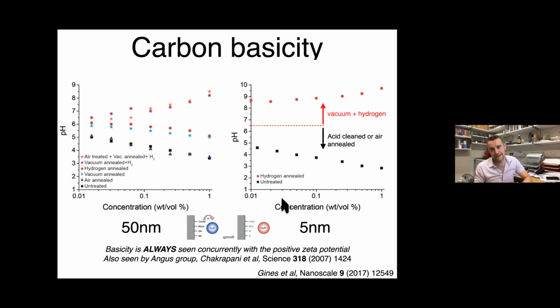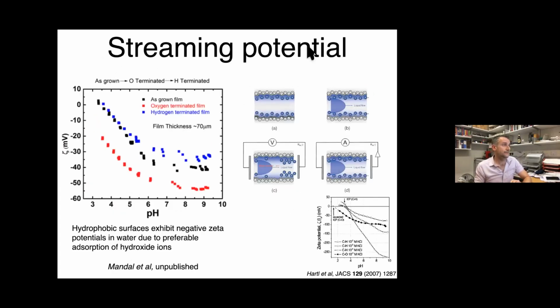And the reason I don't think it's surface conductivity is if you take a bulk diamond and hydrogen terminate it, you don't see a positive zeta potential. So I'll show you that data, right? So here we do streaming potential. This is almost the same as zeta potential, but we're now doing it with 2 large diamonds, right? So I've got, like, in this case, 70 micron thick films. Suman did this years ago. Henry's repeated it on much thicker films, with bigger grains, and sees the same effect. If you hydrogen terminate, you do not see a positive zeta potential. You see neutral, right? And so for me, that's a red flag because there's almost no sp2 on this material.